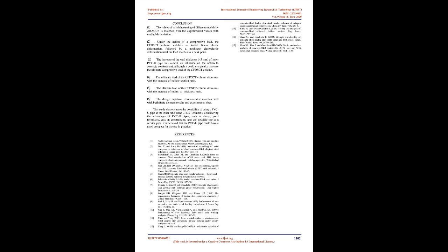4.5 Effect of thickness of PVC-U pipe. The relationship between the ultimate compressive strength of the column and the PVC-U pipe thickness is also almost linear. The innovation of the present study is the use of inner PVC-U pipe, instead of the commonly used steel tube. The PVC-U pipe has lower strength. However, as is demonstrated above, due to relatively small cross-section area, the influence of the strength of the inner pipe on the load capacity of the whole column is not very significant.